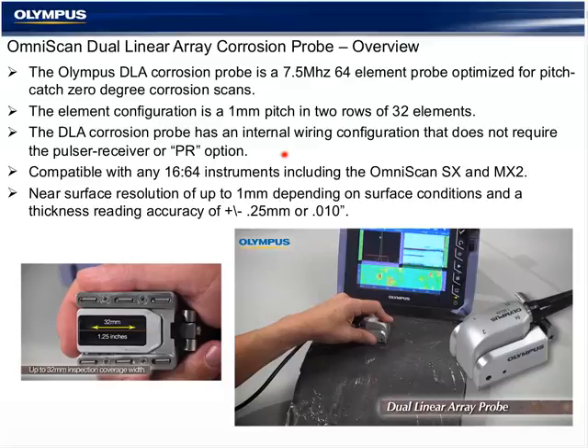The probe is a 7.5 megahertz 64-element probe optimized for pitch-catch 0-degree corrosion scans. That means it has 32 elements on one side of the probe and 32 elements on the other side for a pitch-catch typical of 0-degree corrosion transducers used in both phased array and UT inspection.